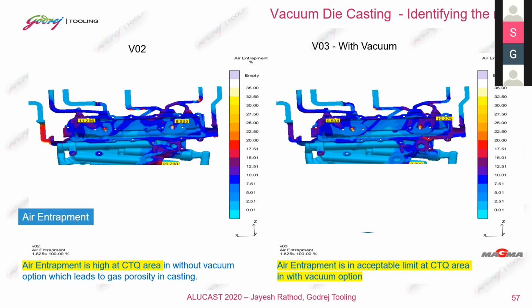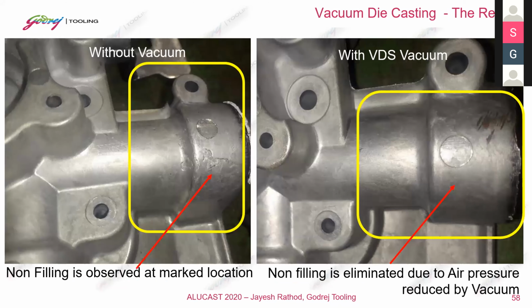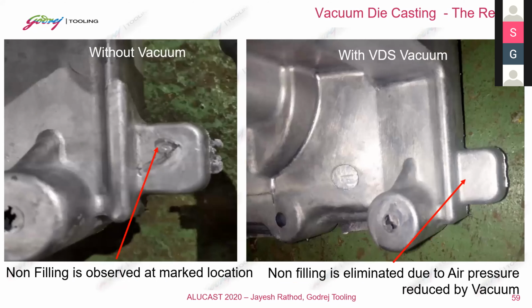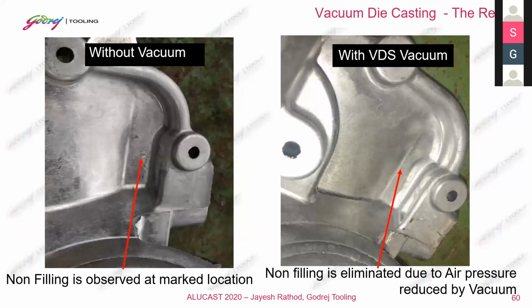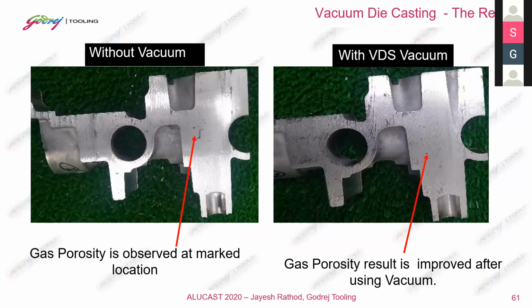And these are the actual casting figures. When we took the trial, initially we started without vacuum, just to see what effect vacuum would have on the casting. Aesthetically, we can see non-filling, and it can be solved. Then again, another area where non-filling has occurred, and it can be eliminated. So these are some of the examples. And then we took the cut section where we could see gas porosity as seen in the simulation study. And with the vacuum system, the porosity has been completely avoided in this area.